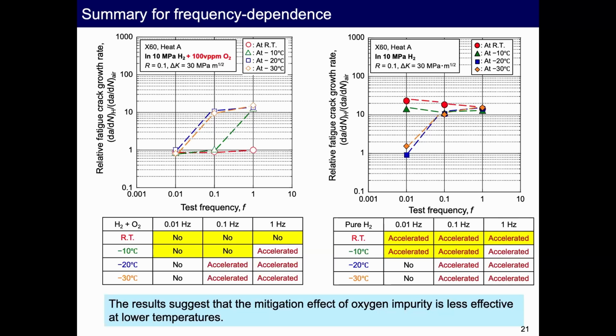So this is a summary of the frequency dependence. This is the result in hydrogen gas including oxygen impurity, and this is the result in pure hydrogen. It's very complicated. I cannot give an interpretation at present. But if we think that the oxygen impurity is the reason, there is some discrepancy. So the result suggests that the mitigation effect of oxygen impurity is less effective at lower temperatures.